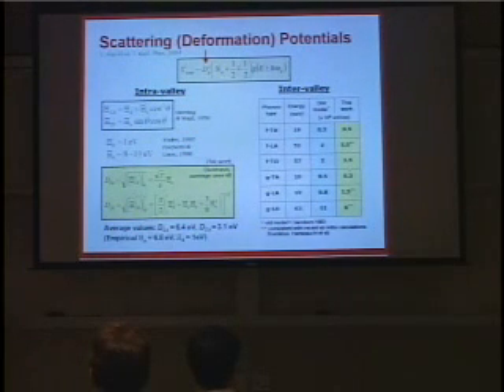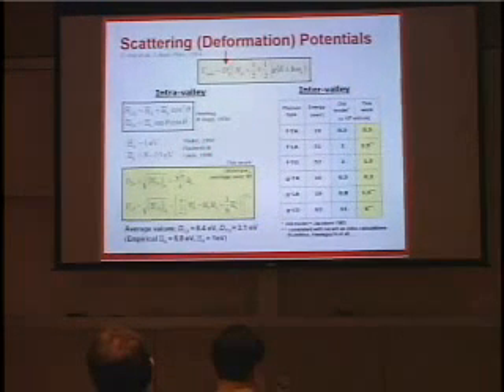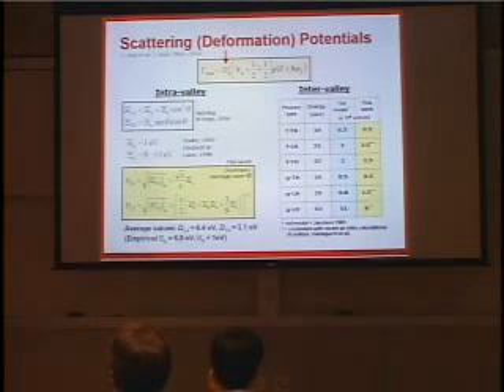Now for inter-valley scattering, there are 3 F-type phonons and 3 G-type phonons. And remember, these are the ones given by geometrical selection rules, so they're pretty well known in terms of their energy. The only thing that's been under some debate over the past 20 years is the strength of each phonon scattering process. And the old model that most of the literature has been using over the past 20 years is Jacoboni's model. And as I will show you, and people have actually known this for a while, Jacoboni's model is not good. It works in bulk silicon, but does not work in strained silicon.